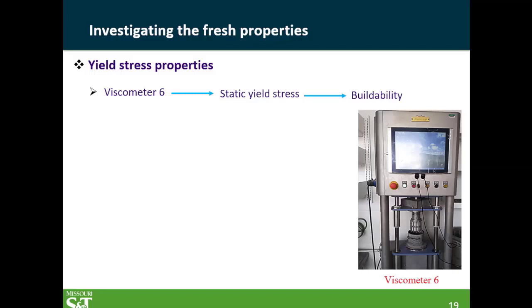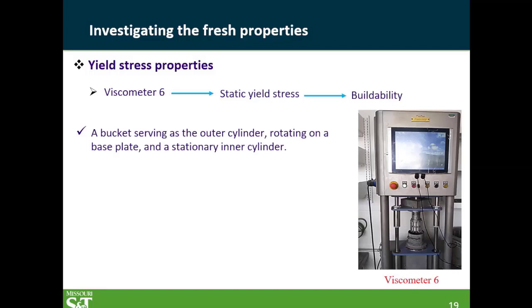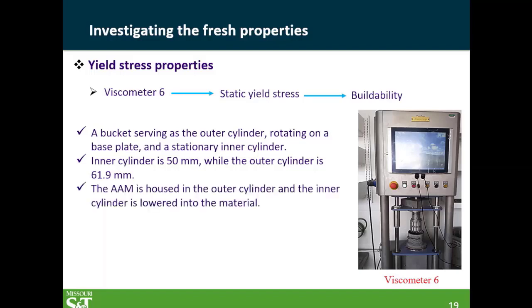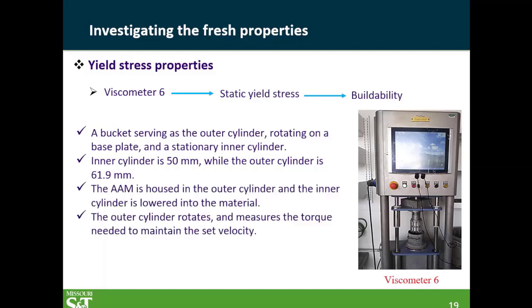So we went to our viscometer. We have viscometer 6 over there. So we did the static yield stress, which again is important for buildability. If you're not familiar with the rheometer, it is 2 cylinders, the outer one and the inner one. We have some dimensions here. The inner one is 50 millimeter, the outer is about 60 millimeter, and then the mortar is filled in between, and then you apply your torque.